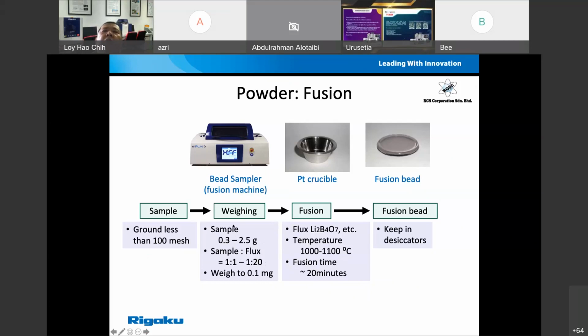Once you mix everything together, the flux can be lithium tetraborate, lithium metaborate, or a mixture of both in different concentrations. Then we put it in the platinum crucibles and heat it to 1000 to 1100 degrees Celsius. The fusion time is approximately 20 minutes per cycle. Once it's done, we get a nicely formed fusion bead, more like a glass bead. This bead you can keep in the desiccator, as I mentioned. If you keep it in low humidity, this bead will last you forever.